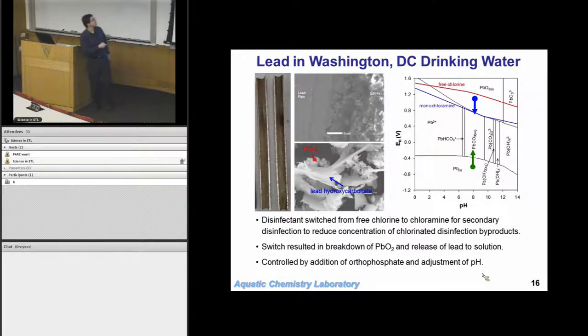This is some work that we did in our laboratory. That's a lead pipe. We cut a piece of it and we look at a cross section of it. So there's the unaltered lead pipe. This is what we would call a pipe scale. And that's only 10 to 20 micrometers thick. A sheet of paper is about 50 to 80 micrometers thick. So pretty thin layer that grows on the lead pipe, and that thin layer has all kinds of little things in it, like lead carbonate and lead 4 oxide. These were things that we were able to make in our laboratory to study this process.